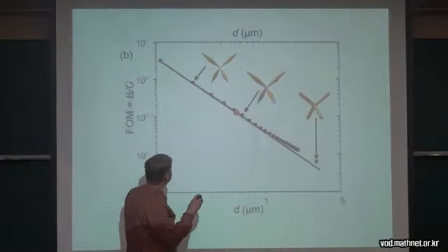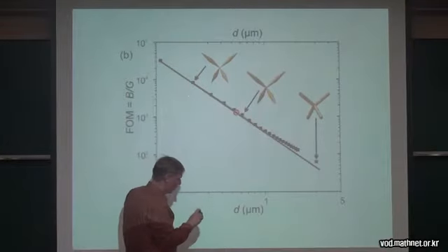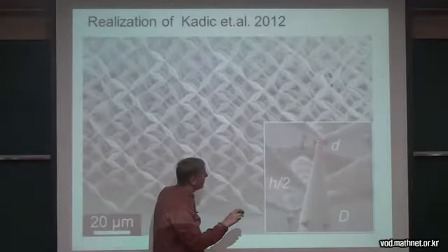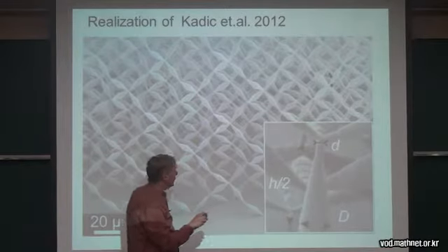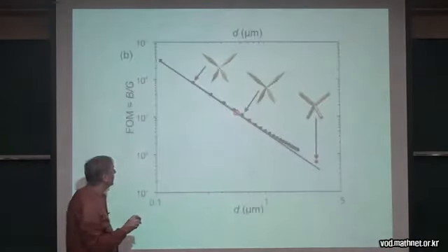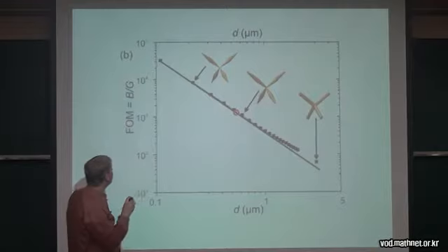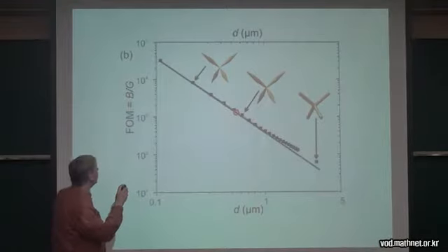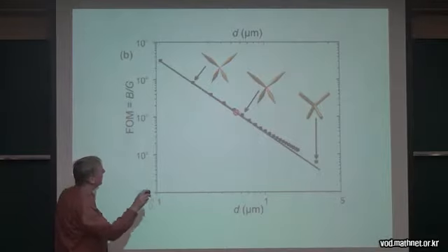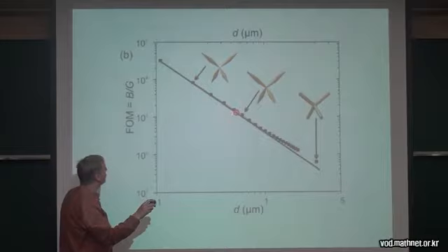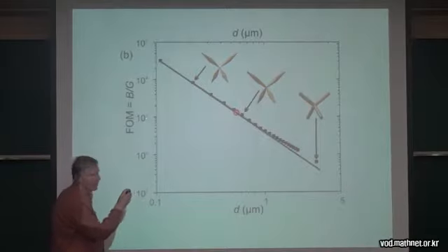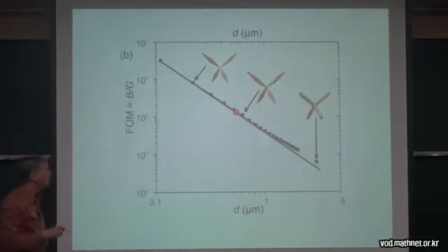And these are numerical results. What controls things is the thickness of this junction here. As you vary that thickness of that junction, you get the figure of merit, which is the ratio of the bulk to shear modulus, gets better and better the thinner the junctions. And this is where that experimental result was, with a figure of merit of about 10 cubed.